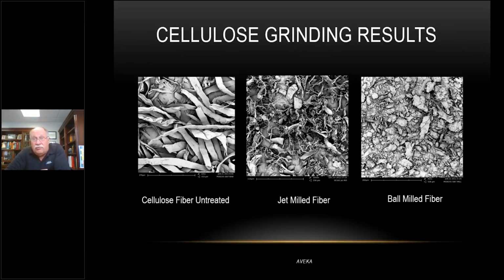There's breakage of these fibers, ripping, I would almost think. But also, if you looked very carefully at this, and you can't see it completely on this, a lot of these fibers are just folded over. It's like folding your clothes and stacking them up. And so it gets smaller and smaller. The particles get smaller. There's some breakage, but it's a lot of folding. But now when we take this ball milled fiber here and we jet mill it, we get this structure. And what we're doing here is we're actually fibrillating the structure, exposing the microfibrils that are in the cellulose fiber to get this structure.